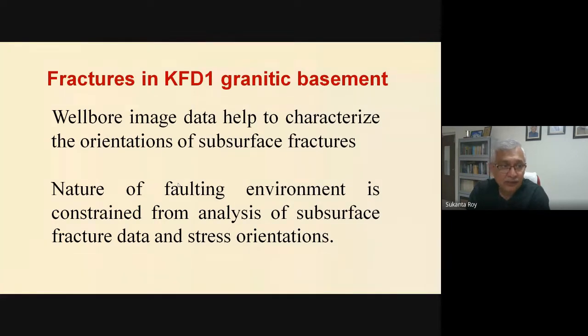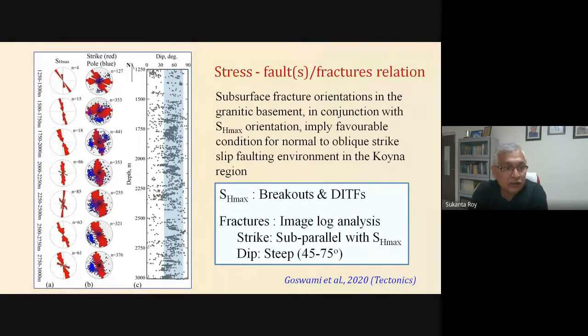Now we looked at the fractures also, because wellbore image data help to characterize the orientations of the fractures, and the nature of the faulting environment can be constrained from the analysis of both fracture and stress orientations. So we identified about 2,200 fractures from the image logs, and the plots are shown here. On the left hand side you have the SH max, in the middle one shows the strike and the pole of the fractures, and the last one the dip of the fractures. You can see that we have here the SH max from the breakouts and DITFs, and the fractures from the image log analysis. The fractures strike subparallel with the SH max in most cases, and they dip very steeply, 45 to 75 degrees.